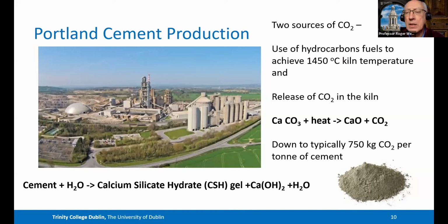of concrete. If we were talking 20 years ago, this plant here, which at the time when it was built, was one of the most modern plants in Europe, in Platin. Before this was built, and indeed throughout Ireland and in many places in the world, we had a rule of thumb of about 1,000 kgs of CO2 per ton of cement. And nowadays in Ireland, the average is give or take 100 kgs less, I suppose, down to around about 750 kgs.